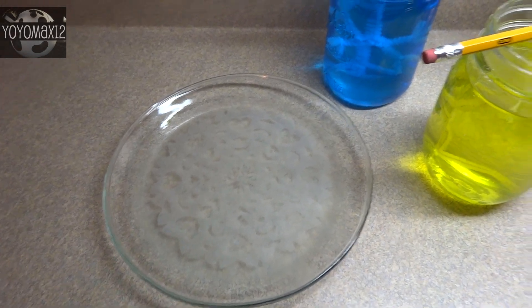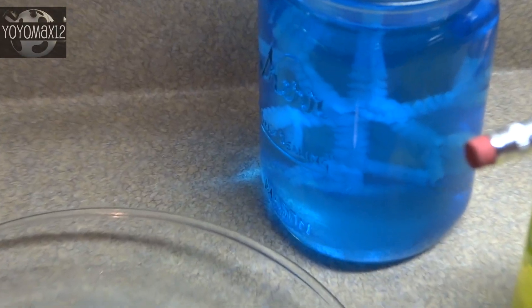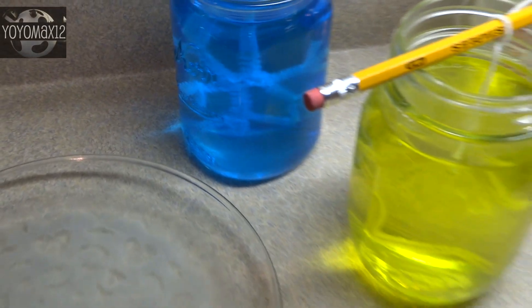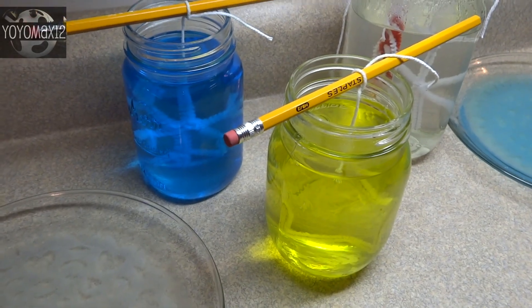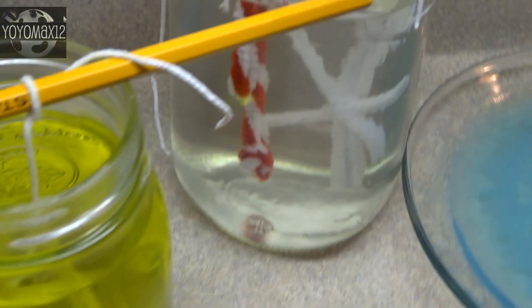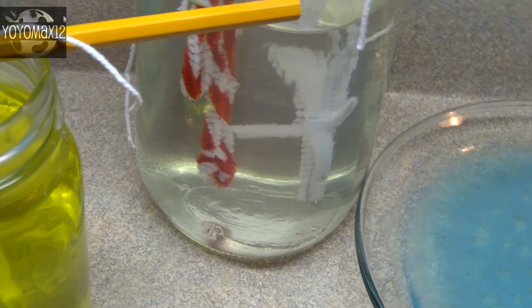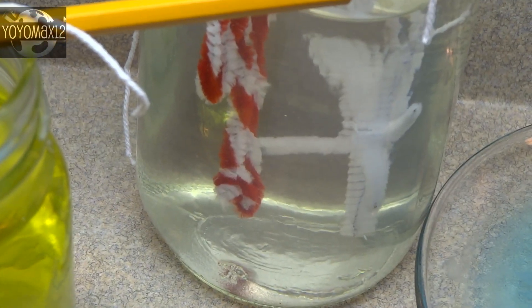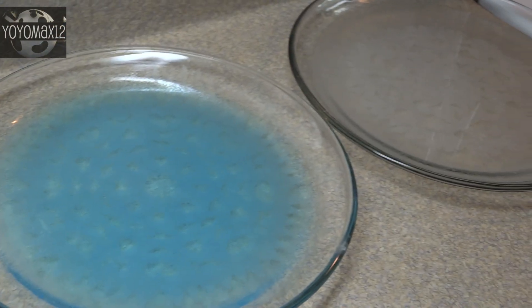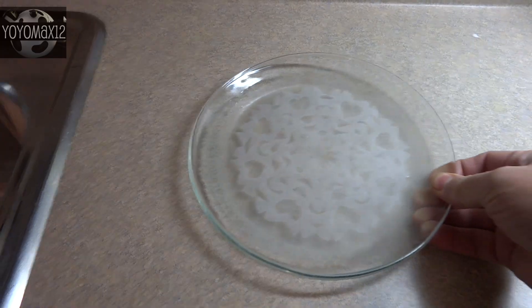Here are just a few of the objects that I used. I did a few of the paper coffee filter snowflakes. I did some in jars, the stars. One of them I put two in. I put a candy cane and a snowflake in. And you let these sit for between three and eight hours depending on how big you want the crystals to be. You should be getting crystals forming fairly quickly. Within a couple of hours they should be quite visible on the objects in the solution. I let mine sit for about three and a half hours and I found that it was a really nice sized crystals.